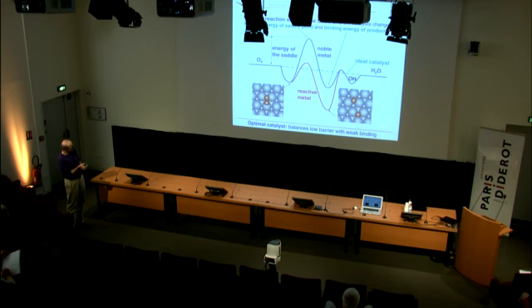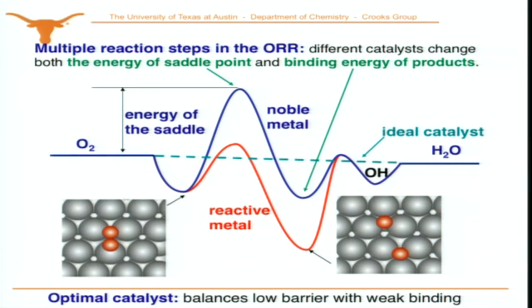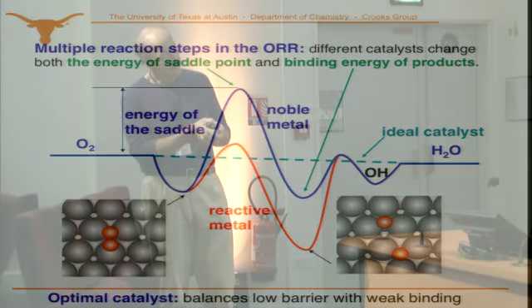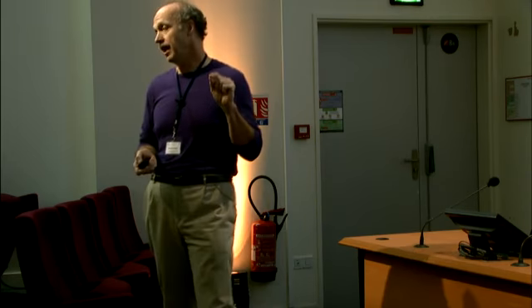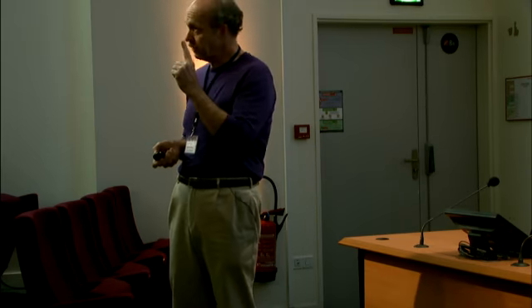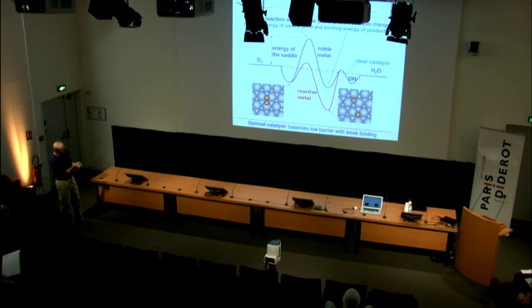So in that case, if you follow the red line here on this sort of Arrhenius type diagram, it's very easy to break the dioxygen bond because that happens naturally on reactive metals. Okay, so that happens easily, but now you fall into this energy well here, and that metal oxide is extremely stable, and the oxygen never leaves the surface. That's bad, okay? The alternative is metals like silver and gold, which don't form oxides very easily. Now we have a big energy barrier to break the dioxygen bond, but if that happens, it's easy to get the product, the hydroxide or whatever oxygenated species are formed on the electrode or on the nanoparticle in our case, off. Okay?